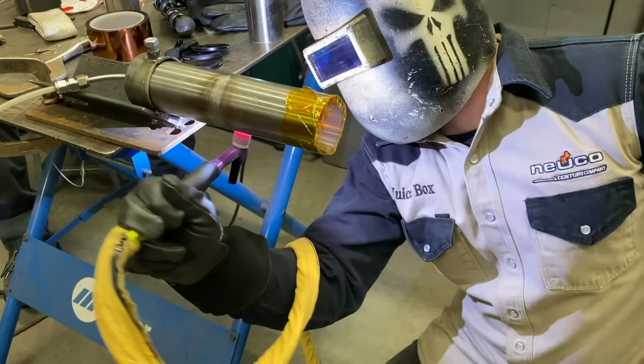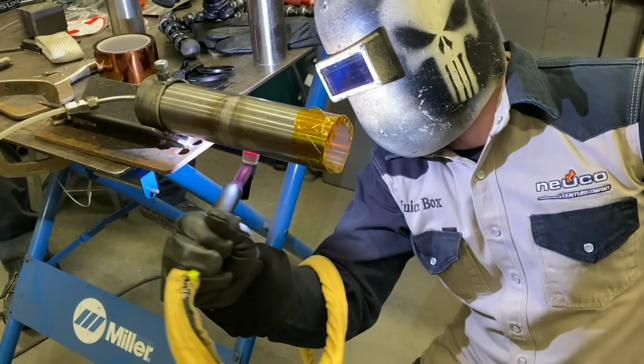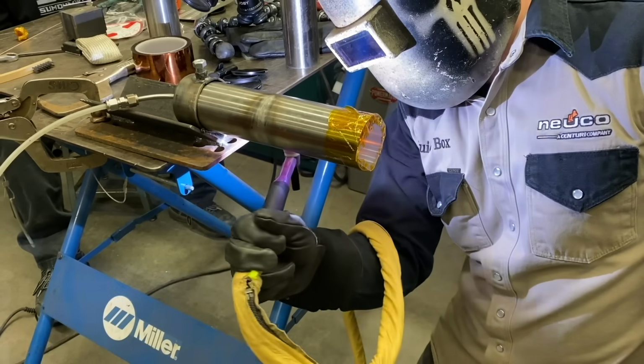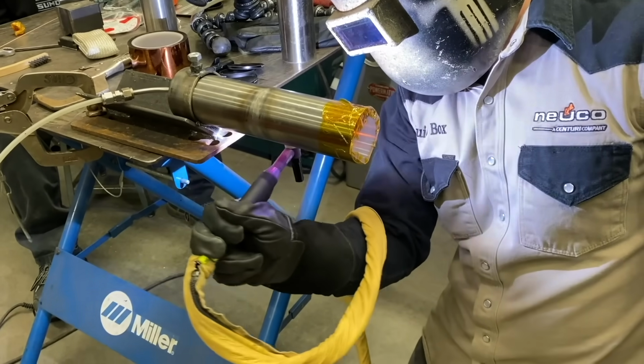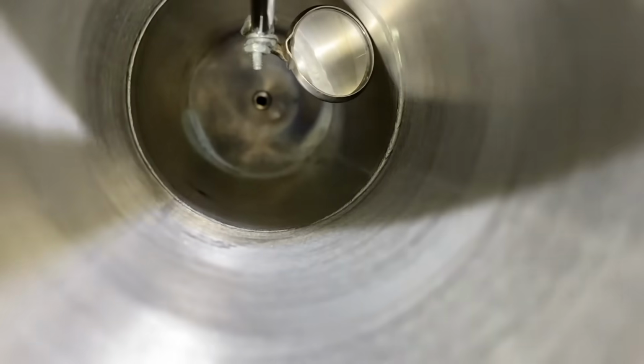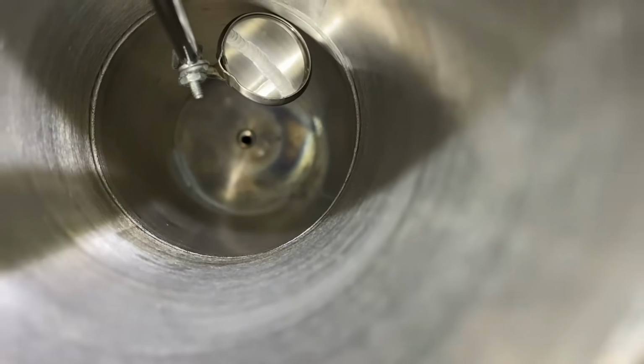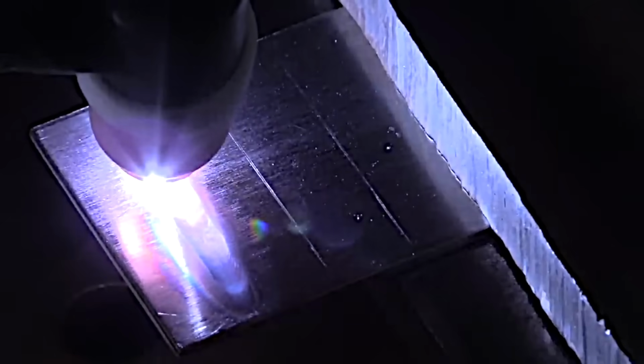For critical welds like this sanitary tubing, you need an argon purge on the inside. There's no substitute for purge gas on the inside there. Without purge gas, you're going to get sugaring, and it's going to be an area where bacteria can grow. Not to mention that, but it's just no fun to weld without a purge. There are certain jobs you might be able to get by with solar flux, but sanitary tubing is not one of those times, and I hate solar flux anyway.